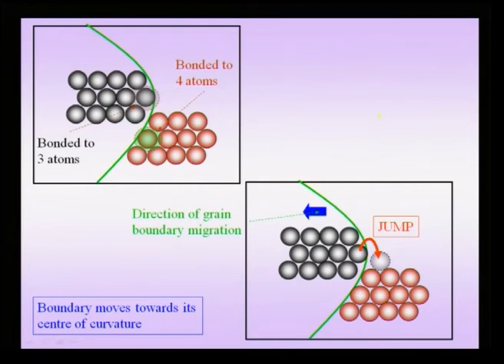So, for instance, to take this schematic, there is a grain boundary here, and this grain boundary separates two grains which I can call grain 1 and grain 2. Because of the curvature of this grain boundary, you can note that the atom sitting on the right hand side, in grain 2, is bonded to 4 atoms. On the other hand, the atom sitting on the left hand side is only bonded to 3 atoms. That means the energy of the atom on the right hand side is lower, it has lowered its energy more as compared to the atom on grain 1, the grey colored atoms.